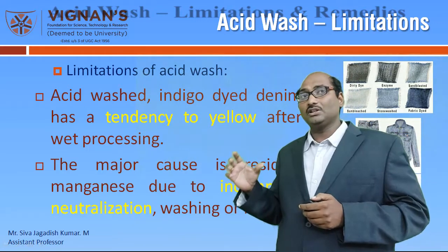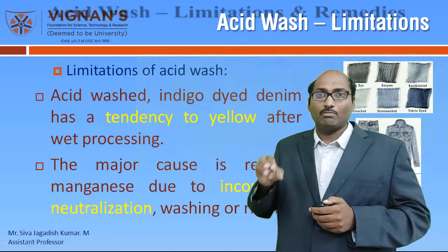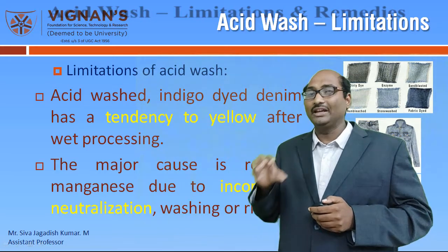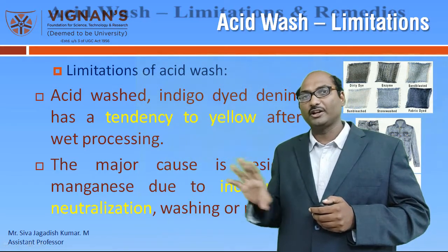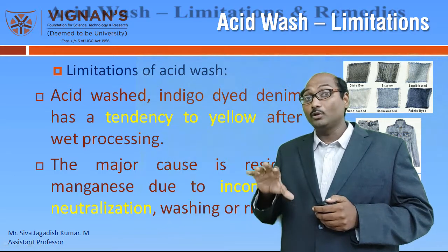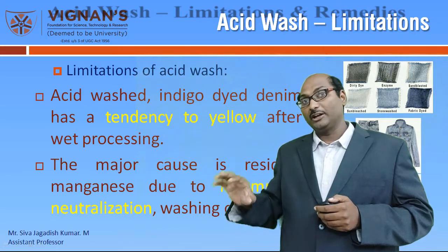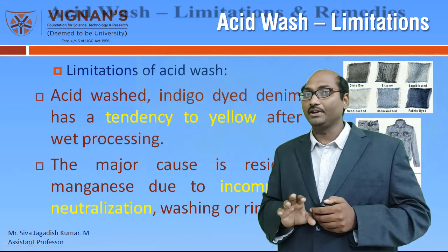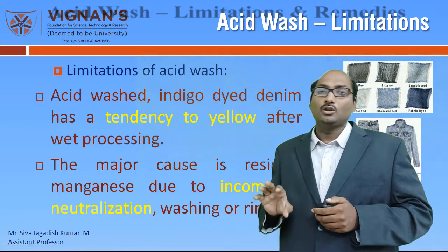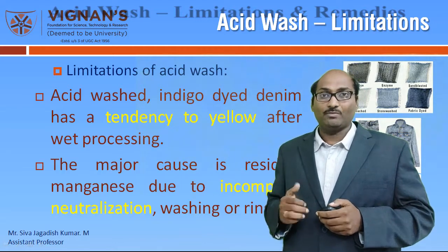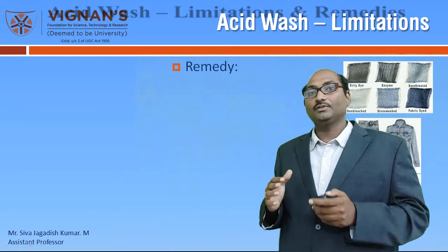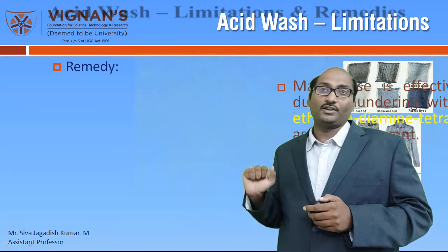The major cause is residual manganese, the manganese which is left due to incomplete neutralization, washing and rinsing. Certain manganese will remain along with these bleach agents and acids, and that causes the yellowing or back staining. So how to resolve this? That is the remedy for this problem.